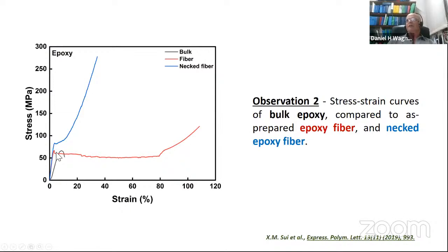And then there is a yield point and there's a very long plateau. And then there is cold drawing. I mean, the modulus increases again, and the strength increases again, and goes quite high, above 100 megapascal. So it's about double the value for the bulk. Then, if you stop the test here, and you have all this necking, you cut a piece and you retest this necked fiber, it goes according to the blue line, which goes now to the sky, really. It goes to 100, 250, 280, and sometimes more megapascal. So this is a huge surprise.